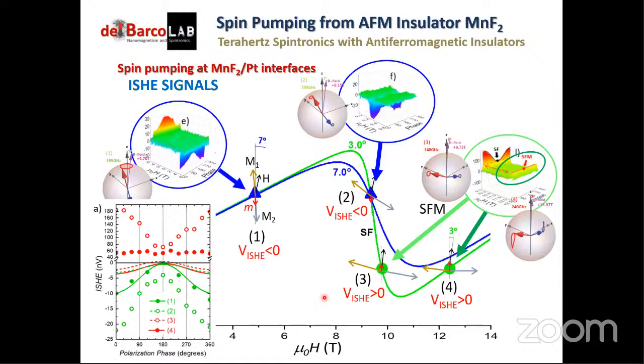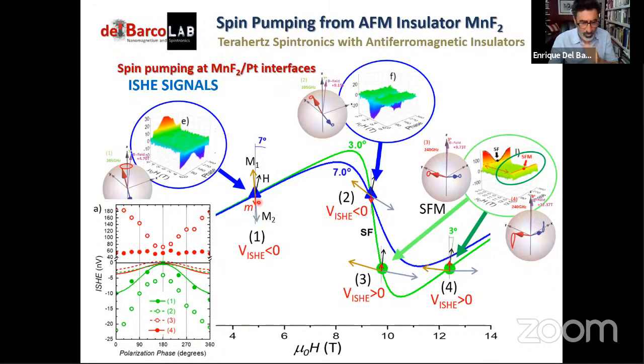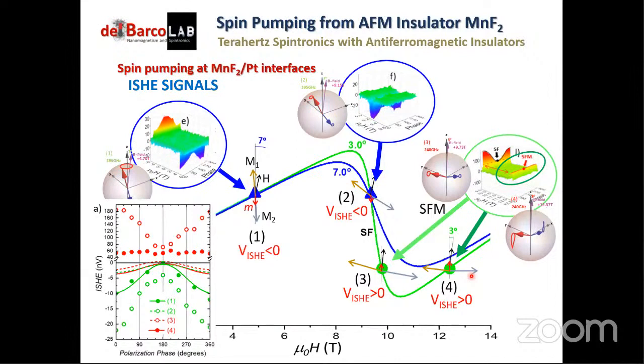Yes. So my belief is that at low fields below the spin flop transition, the excitation is a K0 mode, the main coherent antiferromagnetic resonance mode. When we get beyond the spin flop transition in particular, most likely those are non-K0 modes, and those magnons are most likely generating electric signals as a result of the spin Seebeck effect. That's my understanding, although we don't have conclusive evidence of this, and we want to do some more follow-up experiments. And what is the size of your sample? So how large is the area from which you get your signal? Those are pretty large. They're up to 3 millimeters by 3 millimeters.